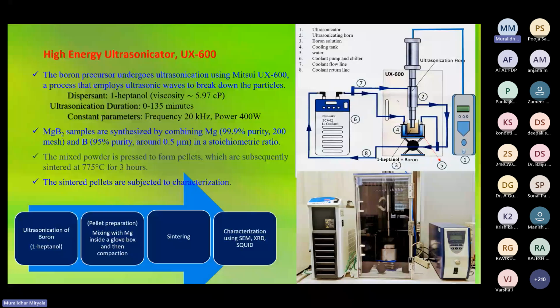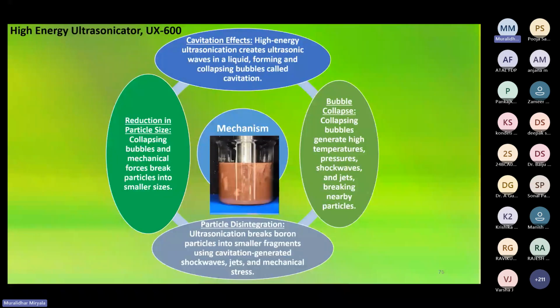Then this slide shows the boron in 1-heptanol. In this right hand figure, you can see that you can control it when making high energy ultrasonification, which generates very powerful shock waves and pressure. As a result, it always heats up this slurry, so we especially designed the cooling system and everything. When your nanoboron is ready, just mix and sinter and make the superconductor very easily. This is the production of the nanoboron.